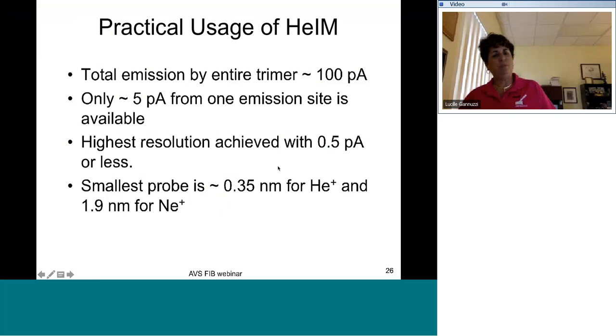As I said, though, because the total emission by the entire trimer is only about 100 picoamps, and you're only putting one of those through there, only about 5 picoamps from one emission site is available. So the highest resolution is achieved with only about half a picoamp. The smallest probe is sub-nanometer, 0.35 nanometers for helium, and 1.9, sub-2 nanometers, for neon. So really for extremely high resolution, nanometer scale work.